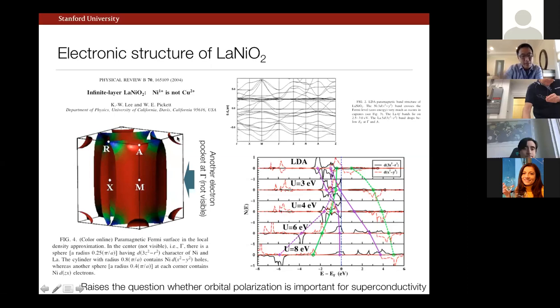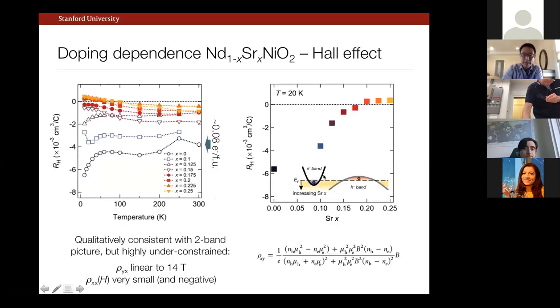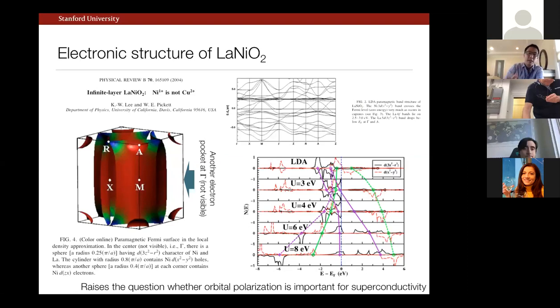And from the hybridization with the 5D states, you have these two little electron pockets. Okay, so in a qualitative sense, this is quite consistent with at least what we see by Hall coefficient measurements. I should also say that in this early work, they tried to investigate computationally what happens as you start to increase the electron interaction. So this is LDA plus U type of calculations.